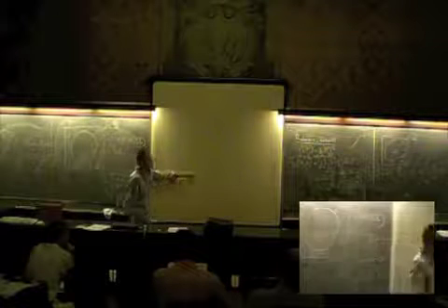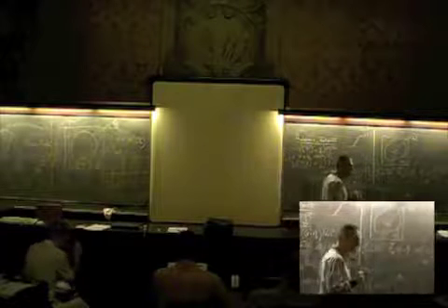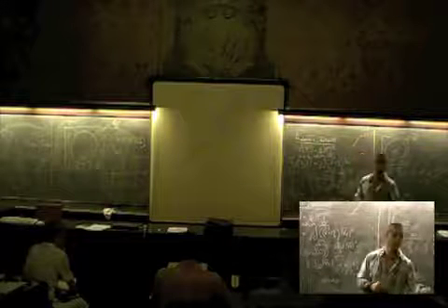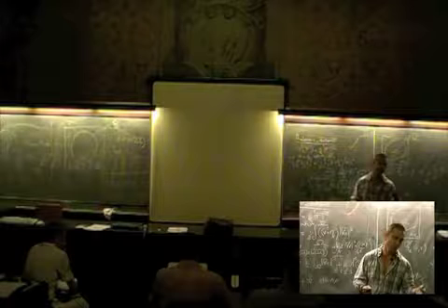Okay, so how are you going to minimize this? You're not going to minimize it directly because we don't know how to, but you're going to do it by alternate minimization. So you fix epsilon. You start with your first guess for U, V, a reasonable guess if you can, and then you minimize in U with that V. Then you take the resulting result, you minimize in V for that U, and you keep on doing this, and you alternate.